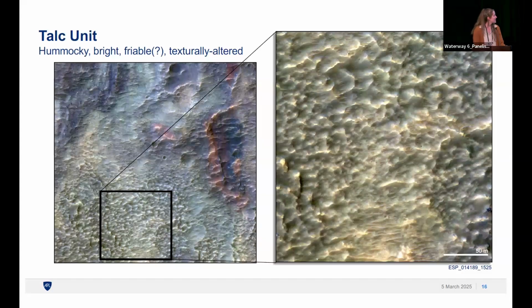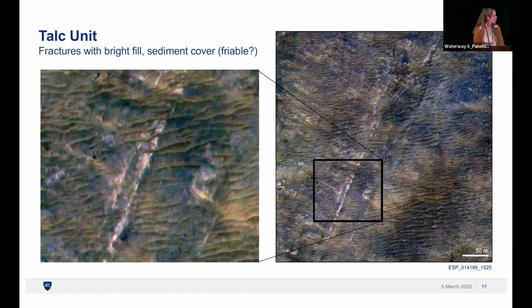The talc unit is pretty yucky. It's texturally altered, pretty friable, bright, hummocky. There's not much going on here in the majority of the spots. So it's frustrating, but we do think potentially in one region, the sediment cover, the friable material, has sort of brushed away, but we still see this talc signature strongly. And there we do see these really bright filled fractures.